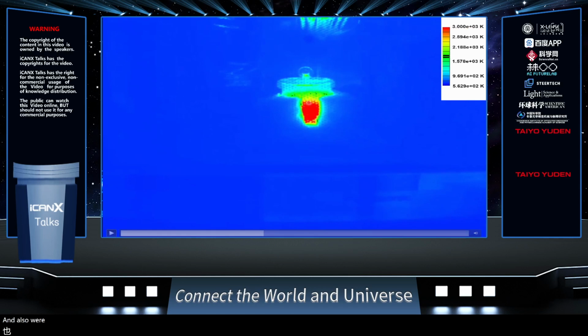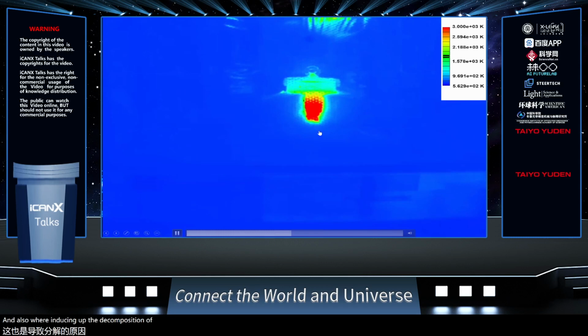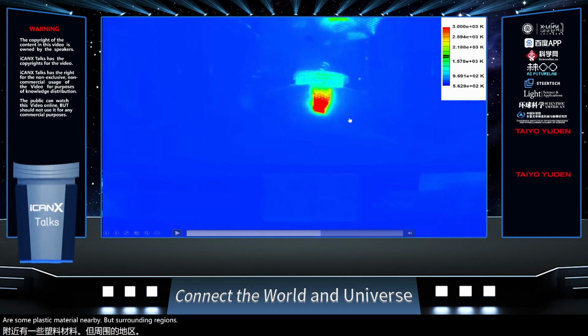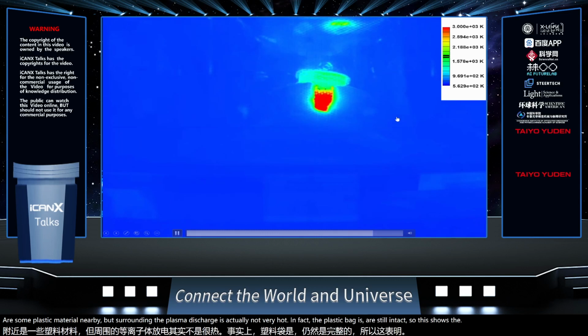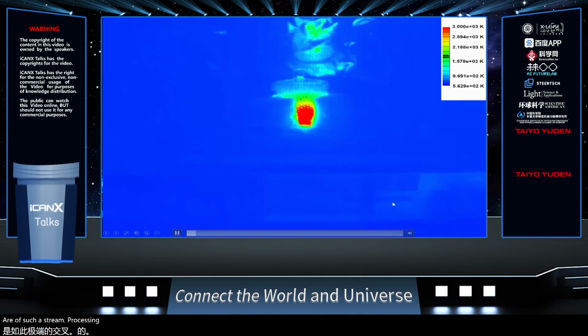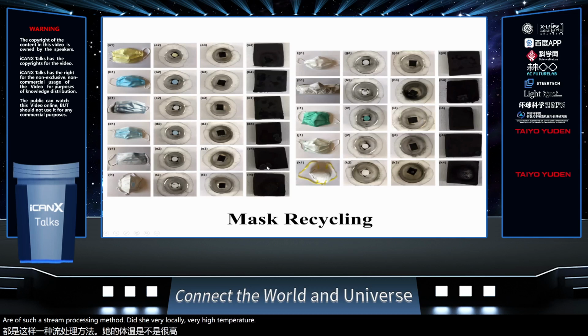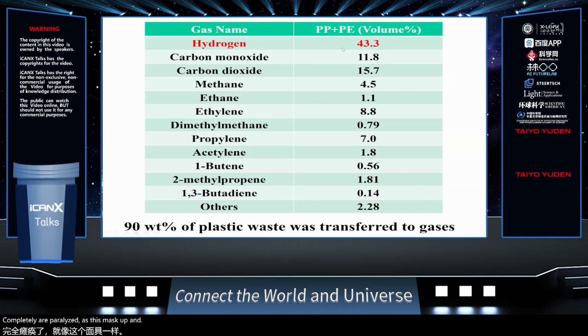And also we're inducing the decomposition of some plastic material nearby, but surrounding the plasma discharge is actually not very hot. In fact, the plastic bag is still intact. So this shows the ability of such extreme processing method to achieve very locally, very high temperature. So for example, in this case, we put these used masks on top of this initial carbon foam, and we're able to completely pyrolyze this mask. And we converted 90% of the original organic mass to small molecules: hydrogen, carbon monoxide, methane, ethane. So these could be used as fuels or as precursors for later chemical synthesis.